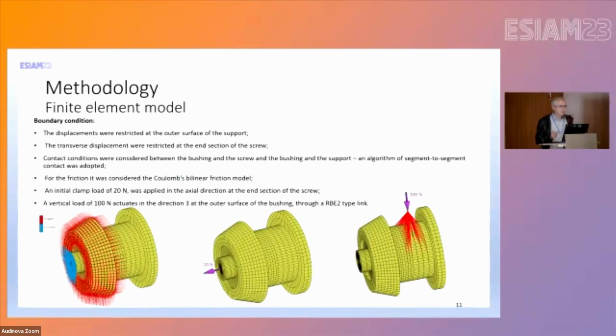As boundary conditions, the displacements were restricted at the outer surface of the support, the transverse in red here. The transverse displacements were restricted at the end section of the screw, in blue. Contact conditions were considered between the bushing and the screw, and the bushing and the support. An algorithm of segment-to-segment contact was adopted. For friction, the Coulomb bilinear friction model was considered.